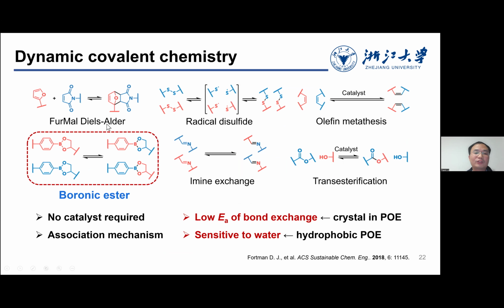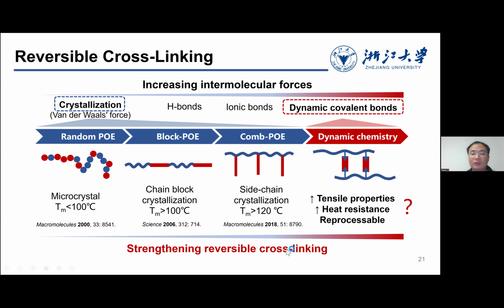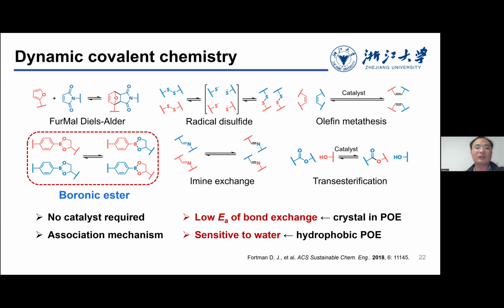For example, the radical disulfide, and also the boronic ester. This kind of chemistry is dynamic. So if you heat it up, it can have an exchange with, for example, the neighboring groups. In this way, you can still have reversible cross-linking, and the strength will be much higher than the physical crystallization. So based on this simple idea, we are trying to introduce this kind of dynamic cross-linking into a polyolefin elastomer network. And during this process, no catalyst is required.